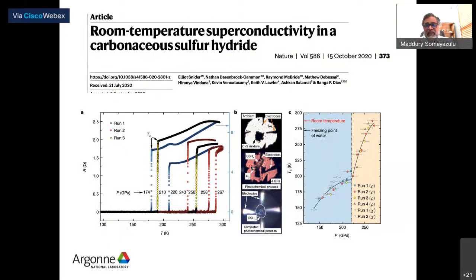Okay, now, of course, I'm getting close to the end. I want to come down to the latest discovery, which is the room temperature superconductivity in carbonaceous sulfur hydride, a brilliant piece of work. And I think it's brilliant from 2 aspects. One is the fact that intuitively you understand from the simulations, which I told you earlier, that replacing sulfur with carbon or doping sulfur with carbon is going to modulate your transition temperature based purely on the fact that if you look at two different binary systems, which is methane and hydrogen, and hydrogen sulfide and hydrogen, you do get a certain amount of systematics.